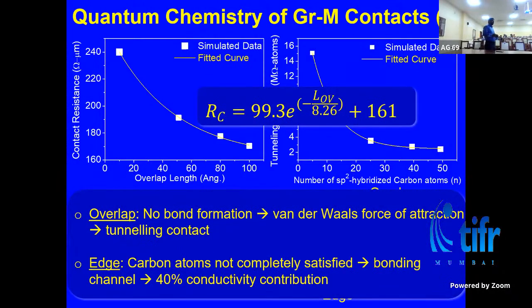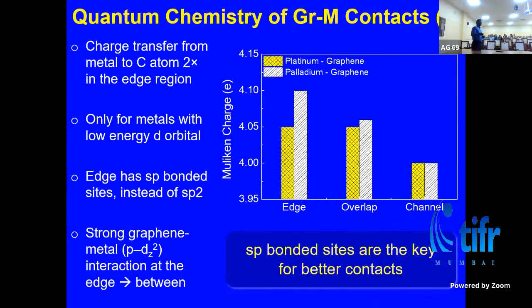So now we figured out that you have this bonding channel based interface of the contact, and the tunneling channel based interface, right? We also studied this as a function of what metals you choose. So what we looked into was Mulliken charge, which basically denotes the extent of charge transfer in that bond formation. If you look into the edge region versus the overlap region, for palladium there's a difference, and in the edge region there's a large charge sharing, which basically denotes the bond formation. Whereas in the case of other metals, like platinum, you don't have any difference between the edge and the overlap, which means they remain the same.